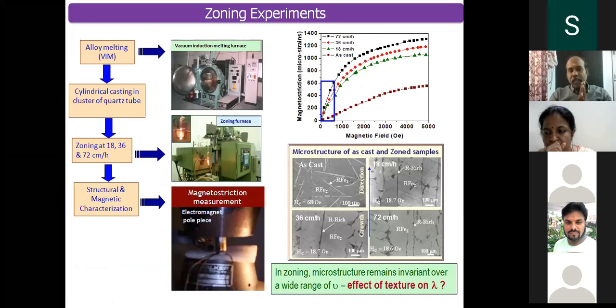The first one is to develop this material by a technique called the zoning technique. The first and foremost thing we use here is vacuum induction melting and casting. Here, in vacuum induction melting, we take the stoichiometric composition of Dy, Tb and Fe in an alumina crucible. We put everything under vacuum and then melt this alloy by powering the induction coil. The melted alloy is cast in a quartz tube. This cast alloy was directionally solidified using the zoning technique. And for this technique, we have extensively used the facilities available at IIT Madras.